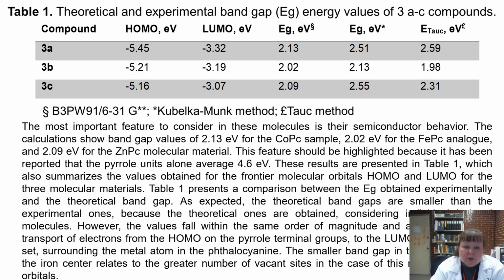The most important feature to consider of these molecules is their semiconductor behavior. The calculations show band gap values of 2.13 electron volts for the cobalt phthalocyanine sample, 2.02 electron volts for the iron analog, and 2.09 electron volts for the zinc molecular material. This feature should be highlighted because it has been reported that the pyrrole units alone average 4.6 electron volts. These results are presented in Table 1, which also summarizes the values obtained for the frontier molecular orbitals HOMO-LUMO for the three molecular materials. Table 1 presents a comparison between the Eg obtained experimentally and the theoretical band gap.